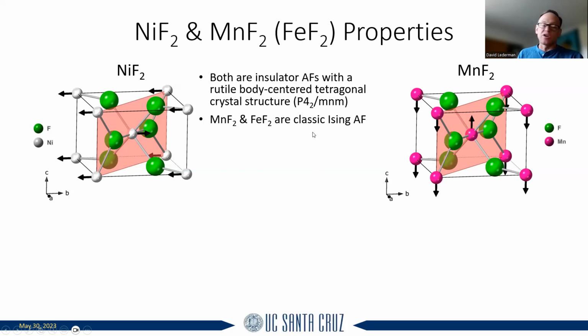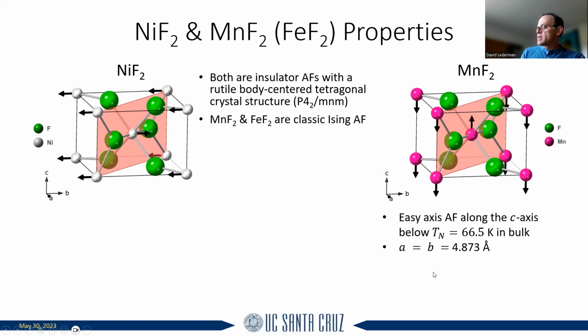And they're considered classic Ising antiferromagnets, which means that the spins like to point up or down. Okay, especially near the phase transition, people have measured the critical exponent of these materials, and it's well known that it behaves very closely to what theoretically you would have in an Ising antiferromagnet. Okay, so for manganese fluoride, the Néel temperature, the ordering temperature, is 66.5 Kelvin.